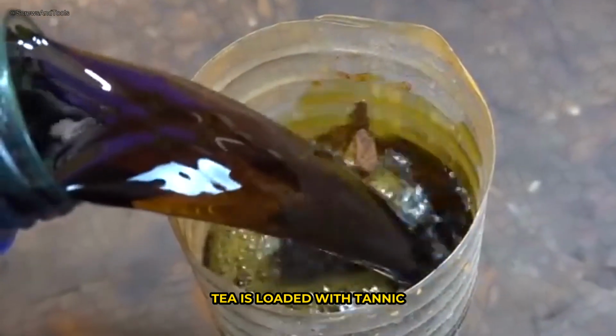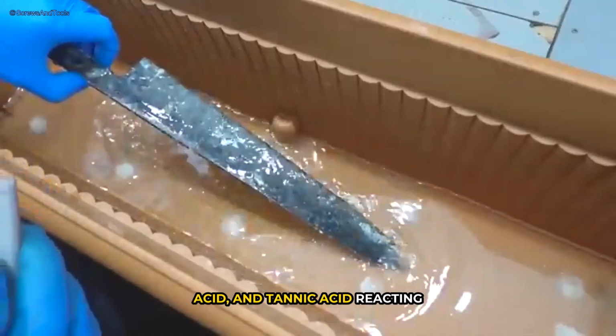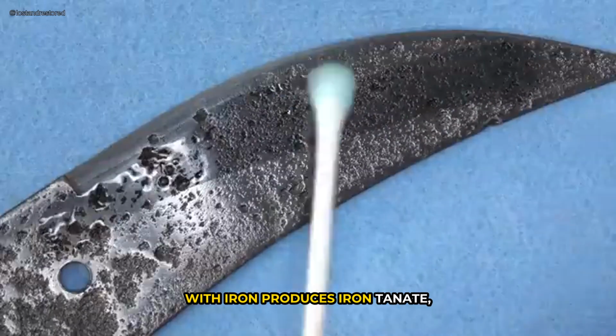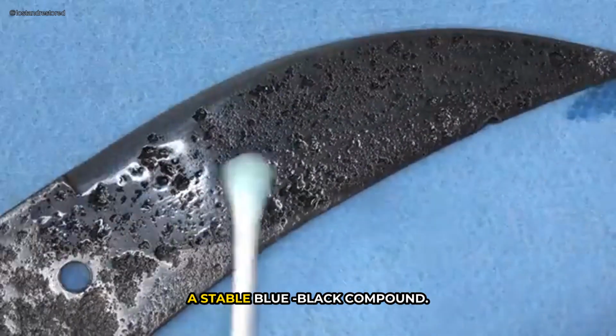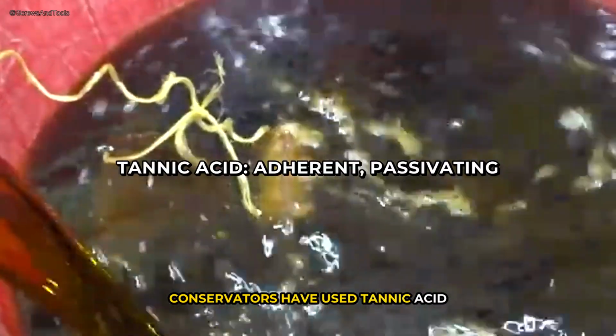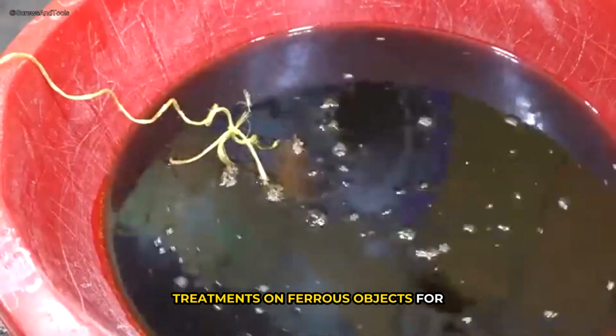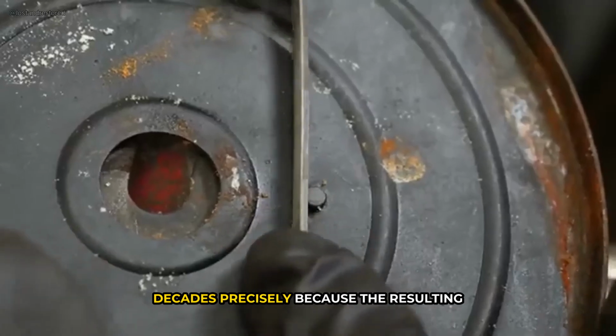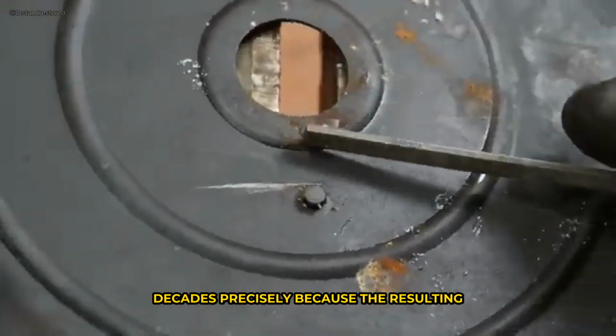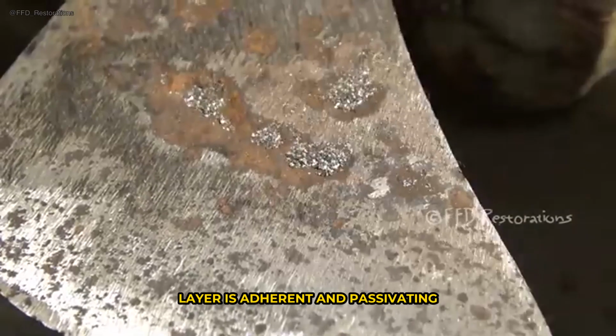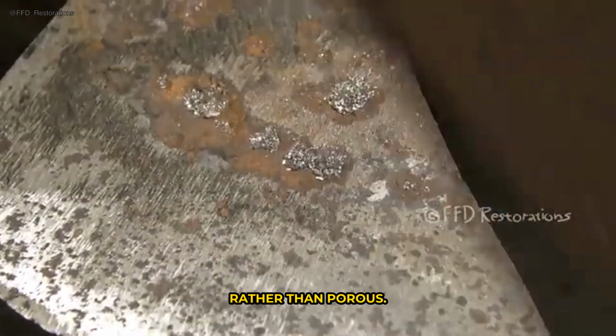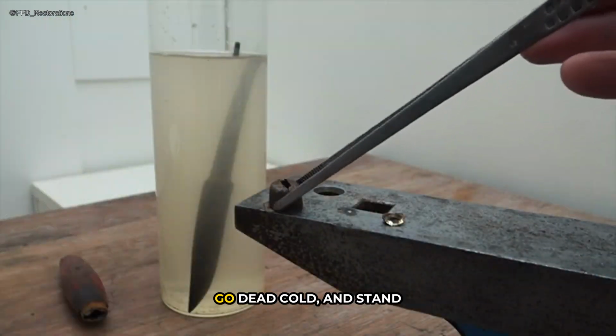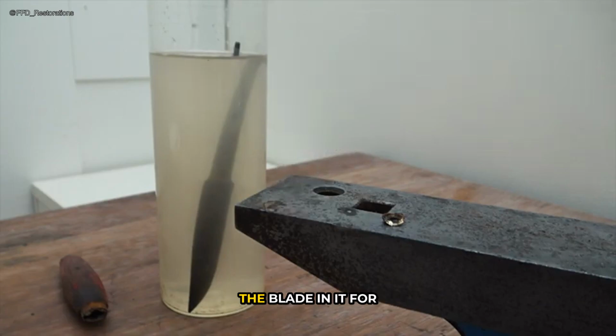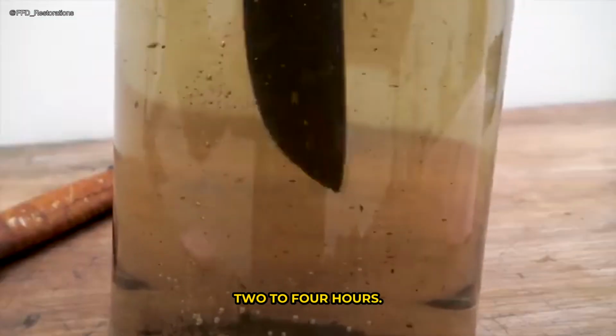Tea is loaded with tannic acid, and tannic acid reacting with iron produces iron tannate, a stable blue-black compound. Conservators have used tannic acid treatments on ferrous objects for decades precisely because the resulting layer is adherent and passivating rather than porous. Brew 4 bags in 2 cups of water, let it go dead cold, and stand the blade in it for 2 to 4 hours.